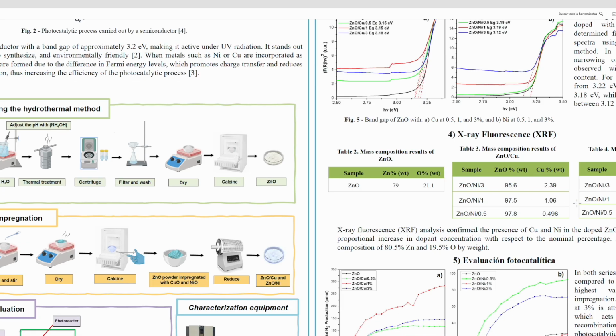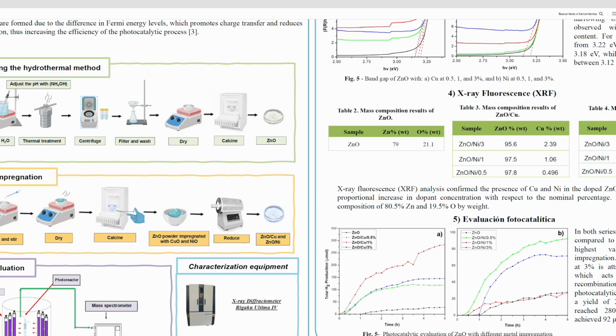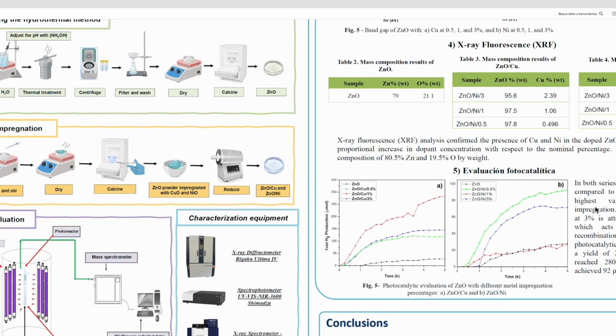The same thing happens in table 3. In the 3% sample, we have 2.39. For the 1%, we have 1.06. For the 0.5, we have 0.496. These are very acceptable percentages, and for nickel as well, a very acceptable mass percentage of the metal in zinc oxide.